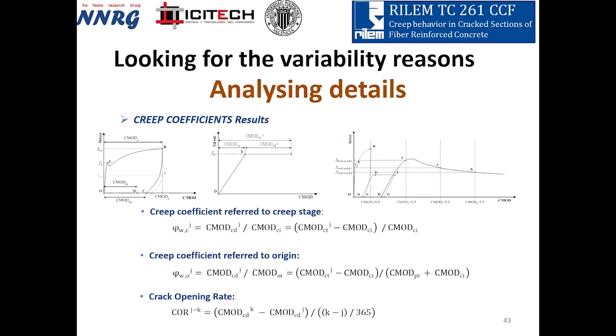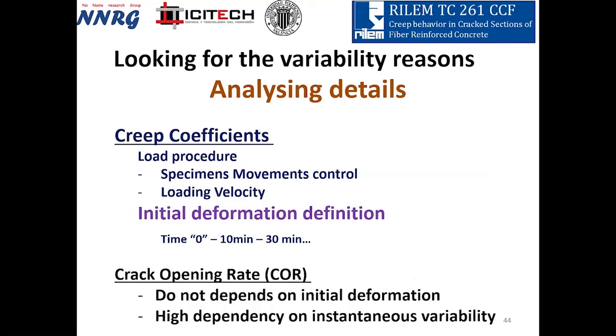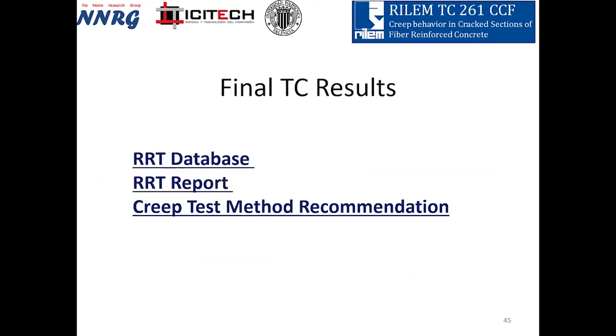Then we also analyzed the creep coefficients, where we had a problem detecting what the instantaneous load application was, because the time of applying the forces was fast in some cases and too slow in others. And then we decided to think of a creep coefficient based on a definition of the time to apply load. Defining the crack opening rate is more difficult to justify because we need a tendency curve to be able to define it. And with that, we have the results.